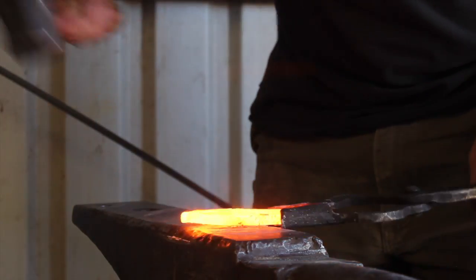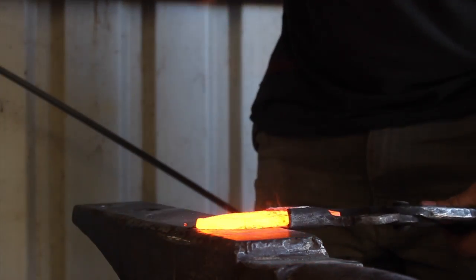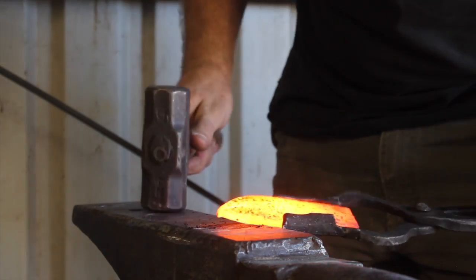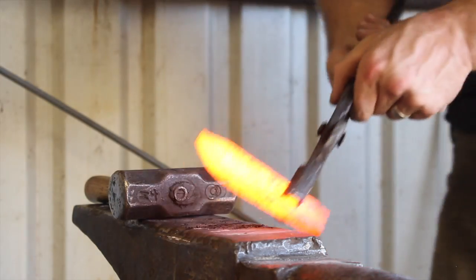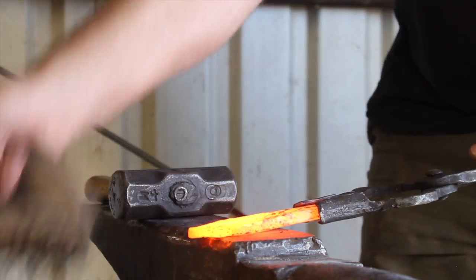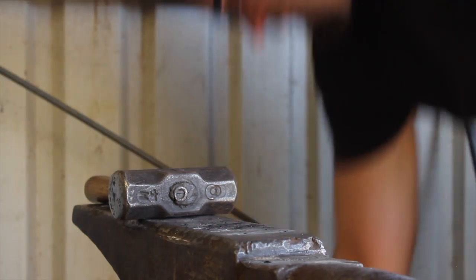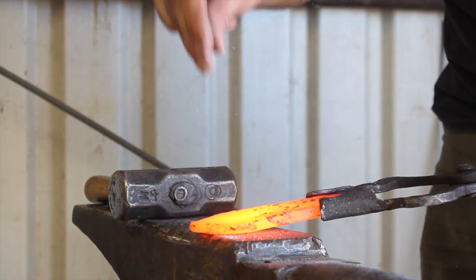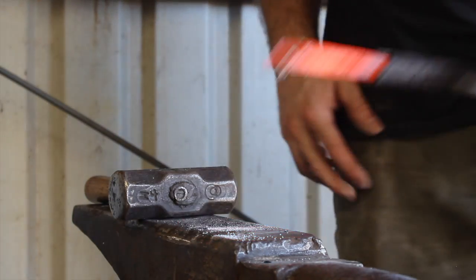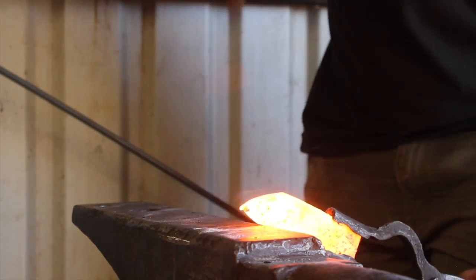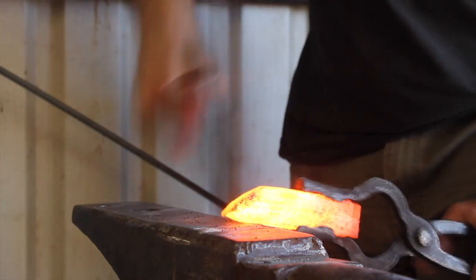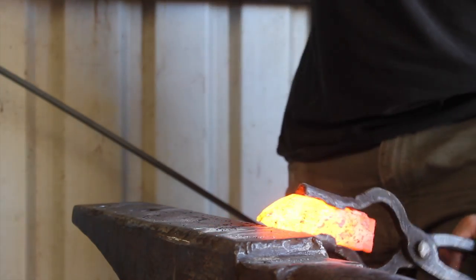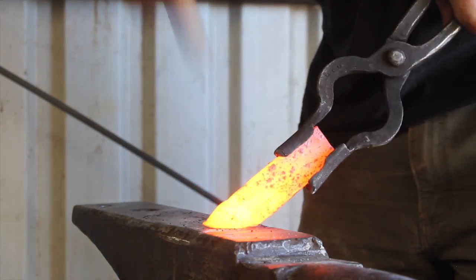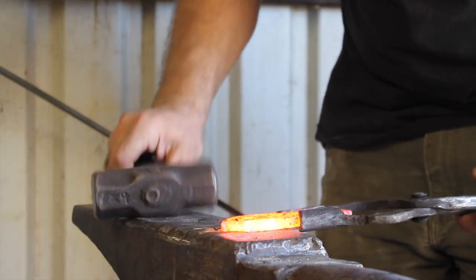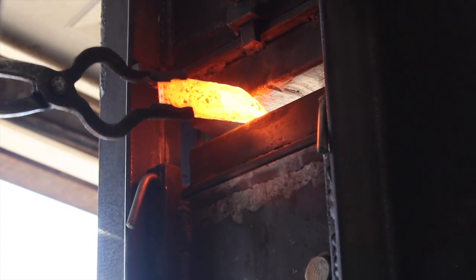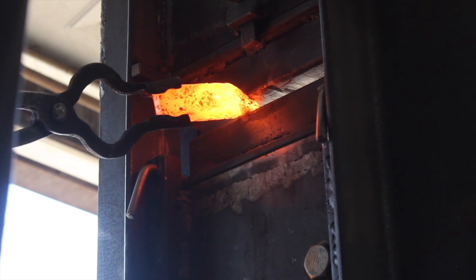pieces, which is unlikely because it's such a narrow piece of material anyway, but I think that helps also because it provides a higher PSI, because where they finally come together and touch right at the tops of those radiuses, and then they just kind of squish together and complete that forge weld as you add pressure. And so what happened is there's a little line as I completed the forge weld here, because that's a radius right there, so it didn't come together 100% on the sides, but I think it was beneficial to make sure that the center of that thickness was well forge welded. So anyway, that's a long explanation, but I think that was an important bit.